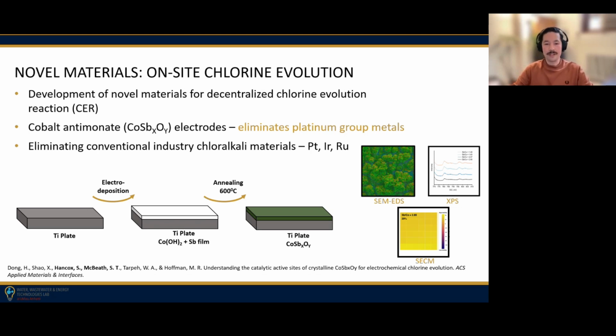From there, we can do a bunch of science with it, like looking at it under a scanning electron microscope and energy dispersive X-ray spectroscopy. So that's SEM EDS, and that tells us the elemental abundance and surface stoichiometry and morphology. So how our antimony spread out over the surface, or how our cobalt spread out over the surface. We can use things like XPS, or X-ray photoelectron spectroscopy, and this will tell us the electronic states and elemental composition. And then we've also been doing things like scanning electrochemical microscopy, or SECM.